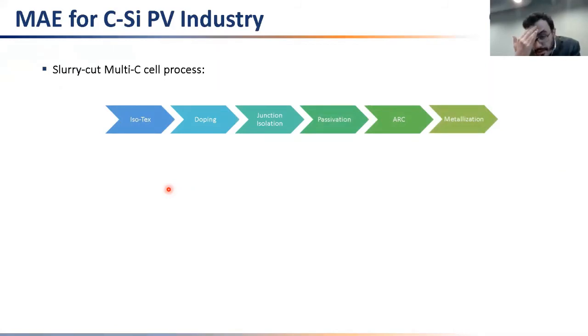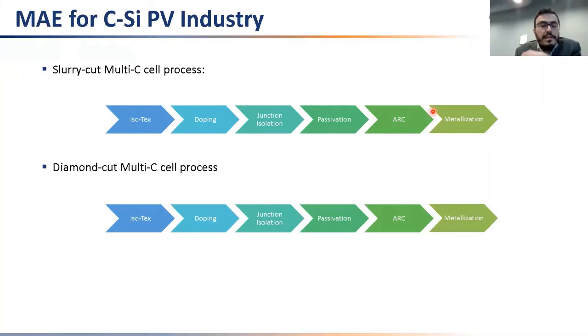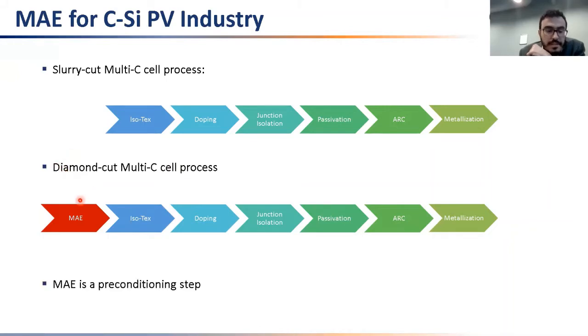In the standard production, we are using isotexturing, doping, junction isolation, passivation, antireflective coating, and metallization. However, in the diamond cut multicrystalline cell process, you cannot use isotexturing directly, so you have to add one more step, which is metal-assisted etching, in front of your production line, and you can start your process with metal-assisted etching and continue production. This means that diamond cut multicrystalline cells can be textured with this metal-assisted etching nanotexturing method. Metal-assisted etching is here used as a preconditioning step, or it can be used as a final step to cover your surface with nanowires. And it creates etch pits on the surface to enable initiation of isotexture.